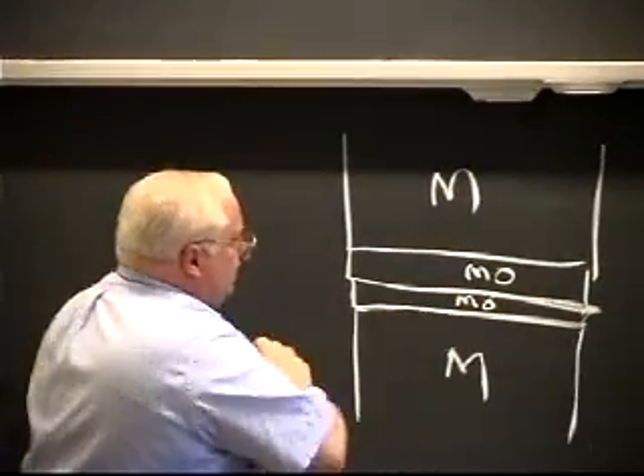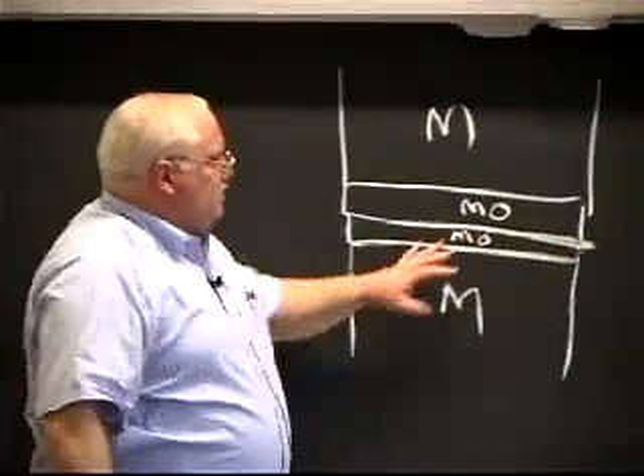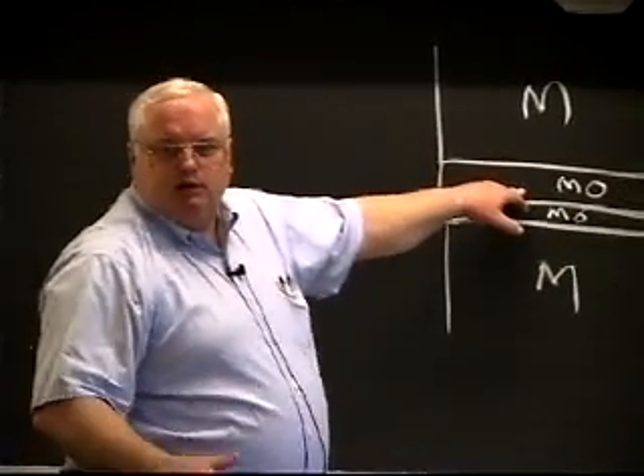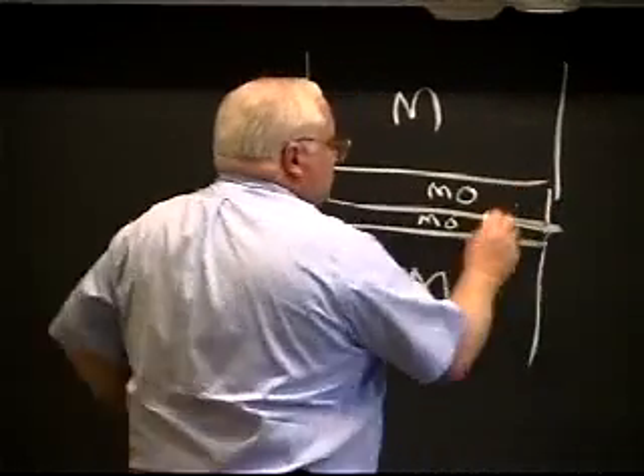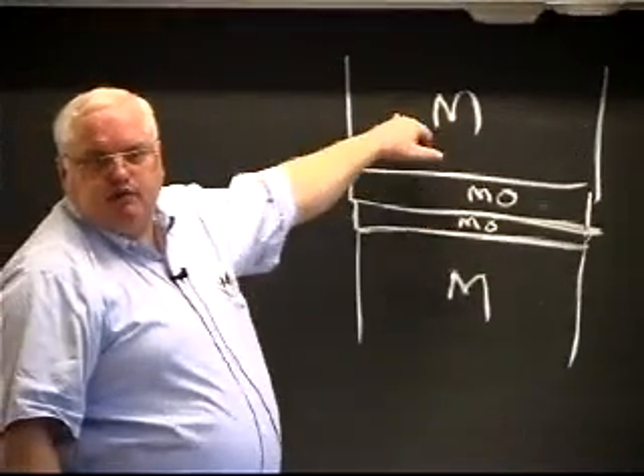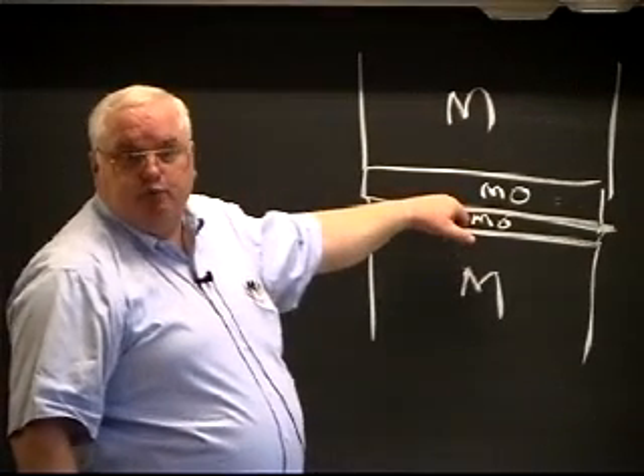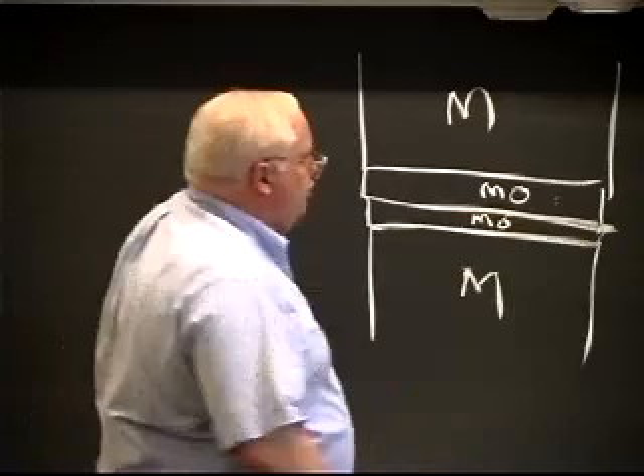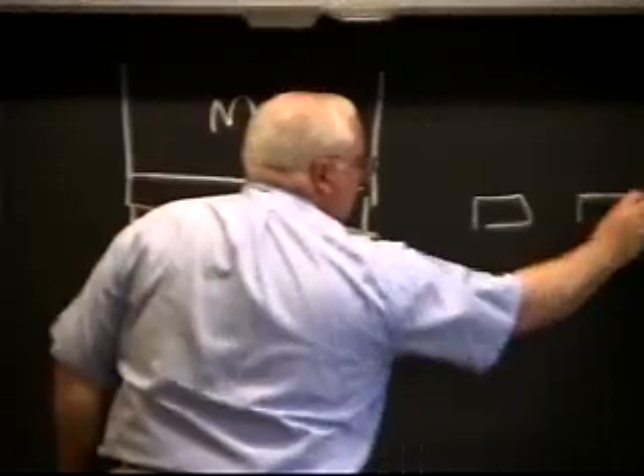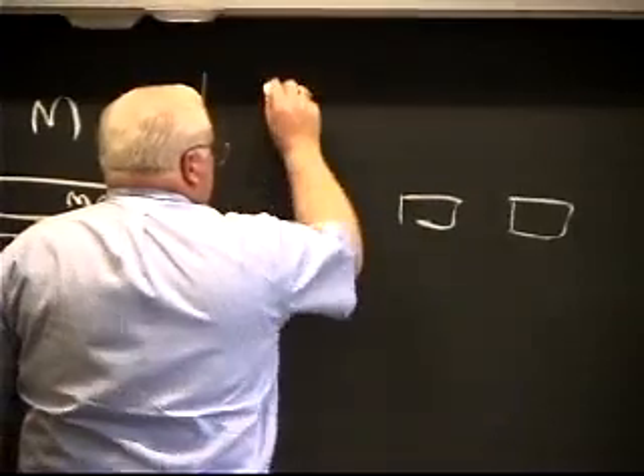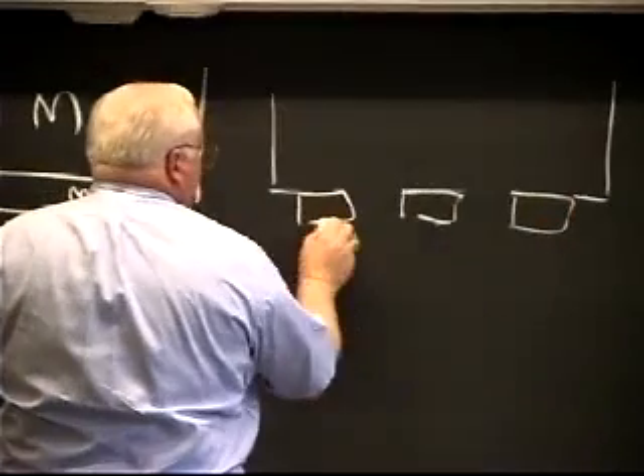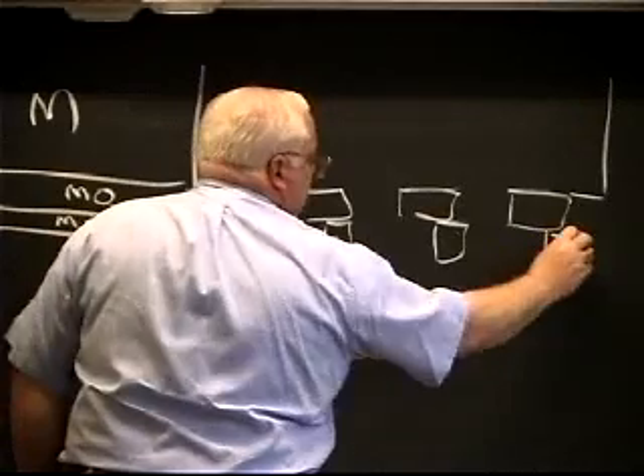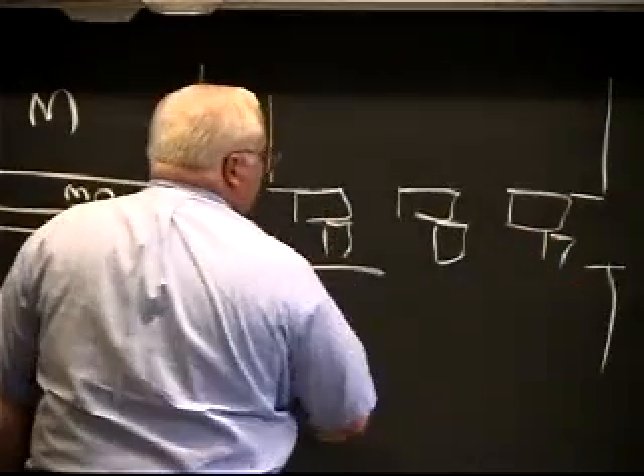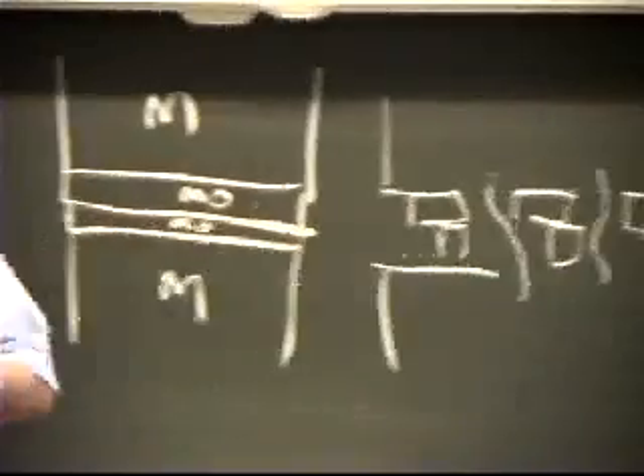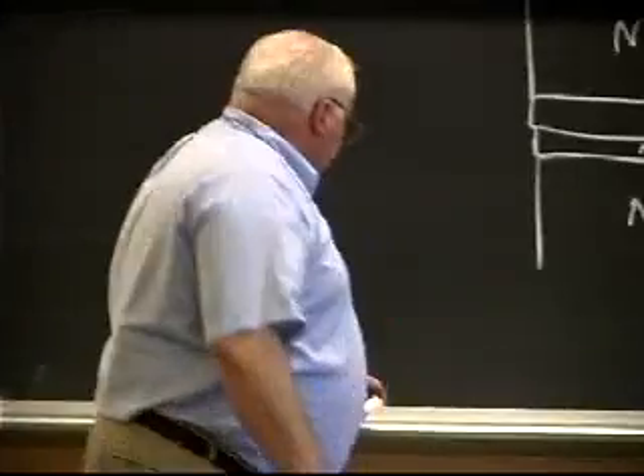And as I squeeze these together or slide them with respect to each other, what's going to give me the easiest cold welding? Well, it's not too hard to understand that if this oxide hardness is much greater than this, then the oxide is going to break up and be brittle, and you'll end up with little islands, little broken islands. You can think of it as ice floes breaking off a glacier or something. And then you got the metal behind it, and hopefully these little ice floes allow the metal beneath here to extrude in between, and you get metal-metal contact, and we know if there's no air around, the metal-metal contact will form strong bonds. And that's exactly what the British did.